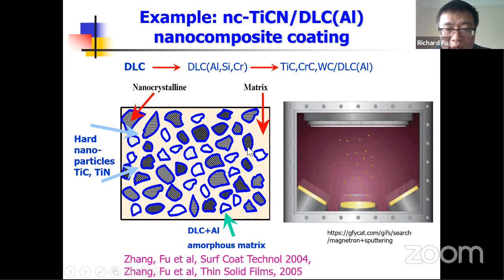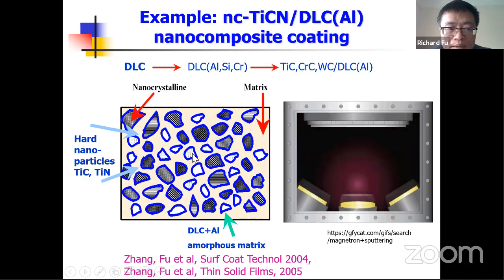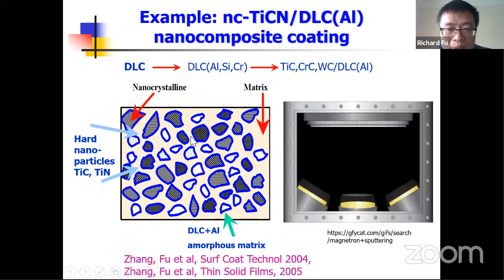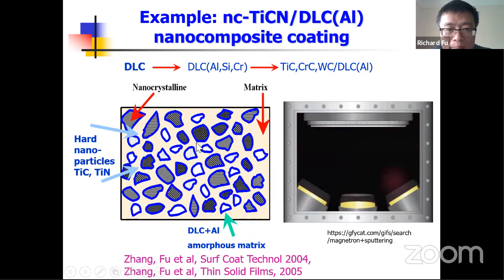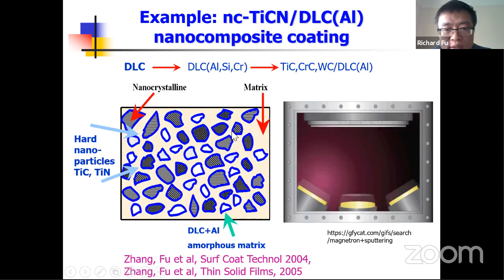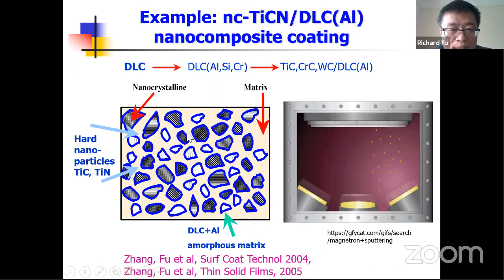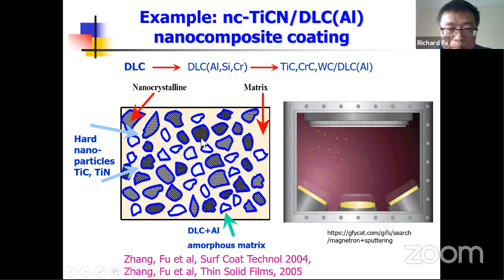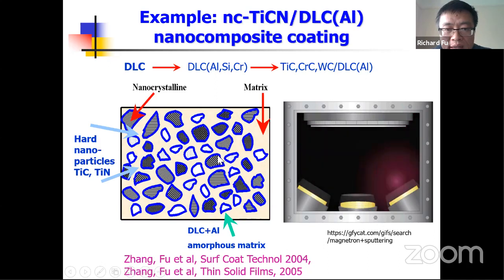And then within this matrix, we have a lot of different nanoparticles. These may be different carbides or nitrides, which are very hard. The size needs to be controlled to about tens of nanometers. The distance between each particle should also be very well controlled, because we want to deflect the crack propagation and increase the propagation path. The orientation of the particles also needs to be controlled, so that they have different directions of control of the strength and hardness.